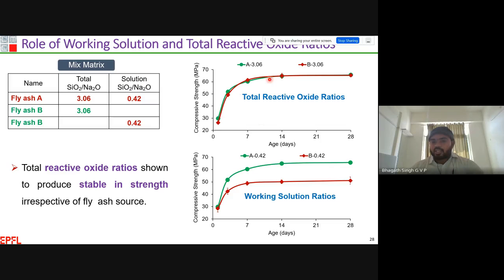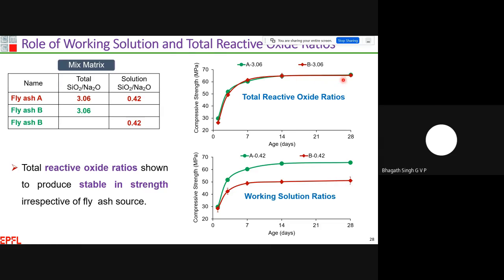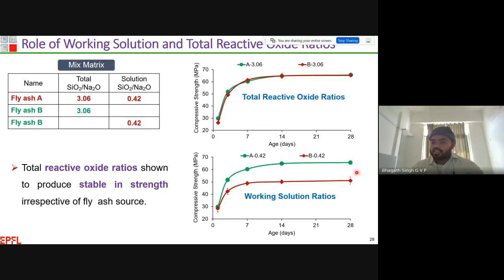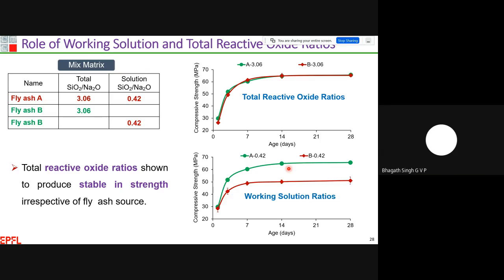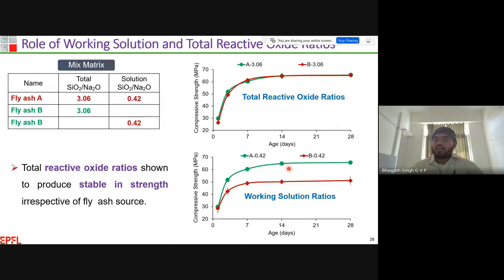And as you can see here, at any particular time, the total reactive oxide ratio mixes for both fly ash sources show similar compressive strength with respect to fly ash source. Whereas the working solution ratios, if I apply them as the literature says, the fly ash A solution ratio to fly ash B, you can see a significant difference in the compressive strength. The results clearly illustrate that the total reactive oxide ratios are key to producing similar compressive strength with respect to fly ashes, not the working solution ratios.